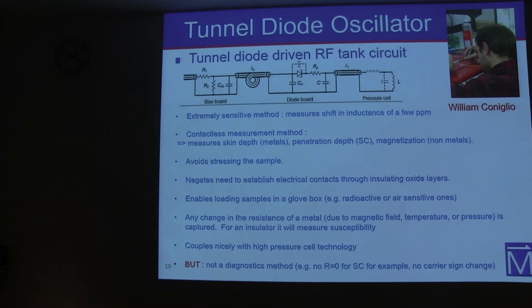We also have other sensitive samples, either radioactive or air sensitive samples. So I work a lot with lithium. Lithium is very difficult to work with, but if we work in a glove box, just dropping a sample in the coil makes it very easy. So overall, it's a very friendly method, but the major drawback is that it's not a diagnostic tool.